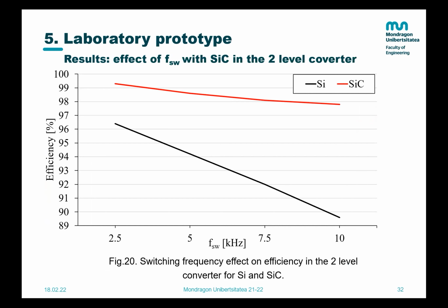So we also analyzed the effect of the switching frequency in the two-level converter. We compared the efficiency of the two-level converter with silicon and with silicon carbide with increased switching frequency. And we see that the silicon carbide keeps a very high efficiency, around 98%, even at high switching frequency, whereas with silicon, the efficiency drops drastically when you increase the switching frequency. So we verified the results obtained by the LCoE calculation tool. We can still have a high energy output with silicon carbide, even at high switching frequencies, and reduce the filters, for example.